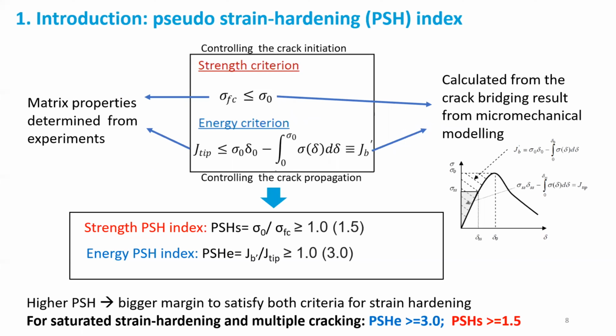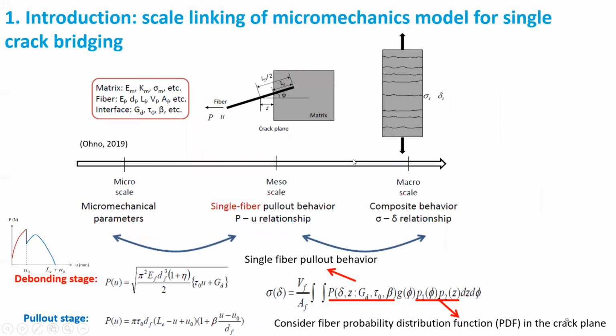For the calculation of the PSH indices, we use the matrix properties determined from experiment. This is the first cracking strength of the matrix, and this is the J tip of the matrix. We also use output from the micromechanical modeling, on the right-hand side here, which is the fiber bridging strength and also the maximum complementary energy.